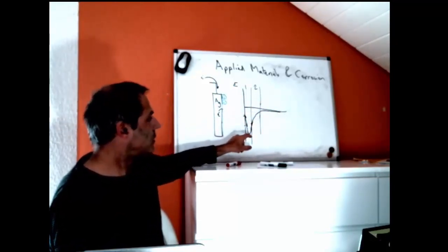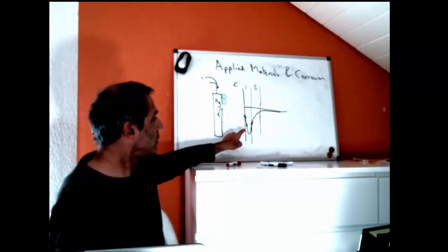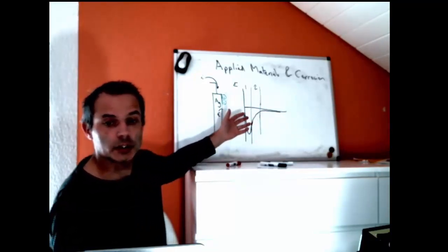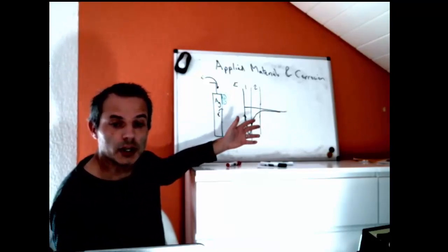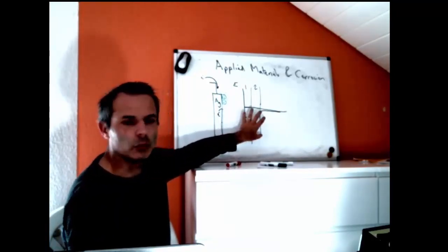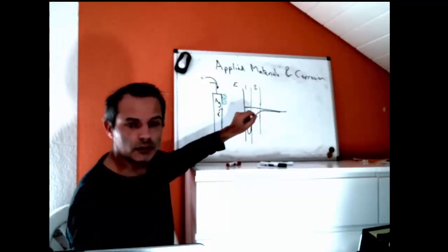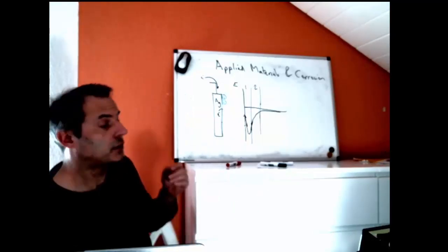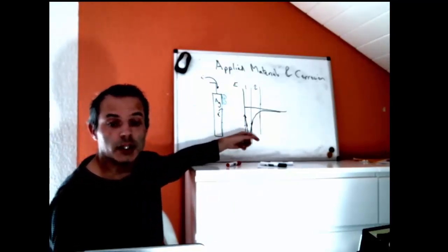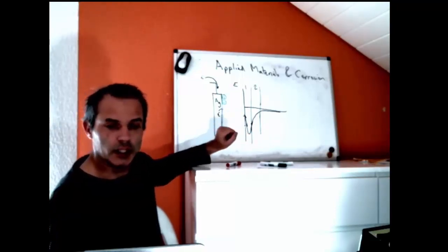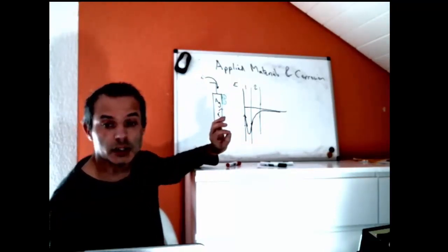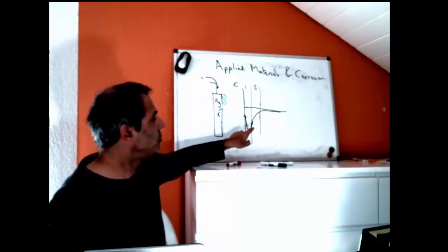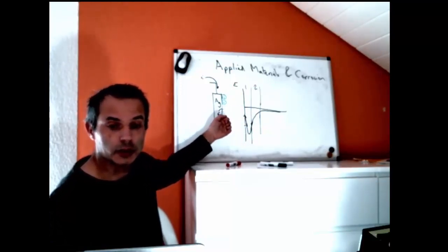That means that our electrode has a thing called a double layer on it. The first layer being adsorbed ions and the second layer being a decay function of the voltage, depending on how many ions we've got in solution that are getting in the way, that are interfering with voltage getting through to the outside, with the field affecting the liquid out here. In some cases, the apparent voltage close to the electrode is actually the opposite of what we think the electrode is. So if we make this silver electrode slightly positive by taking electrons away, it would still be negative compared to the solution because of the chloride ions attached to it.